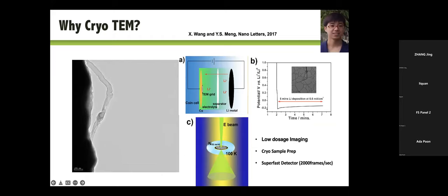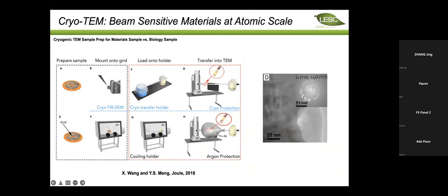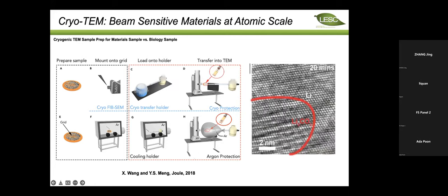And we reviewed in our work early on that you have to develop very carefully the workflow to prepare the TEM samples. One can choose to use the freeze plunge method, which is borrowed from the biology field, or we can use our material science way of preparing the battery materials to study lithium metal. So lithium metal can be imaged in the room temperature TEM if you can find ways to isolate it from lithium carbonate, lithium fluoride, all those SEI components.